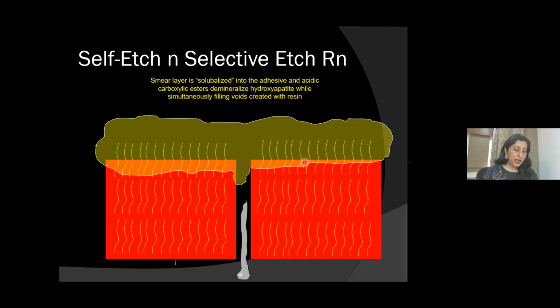And now you have to take a steady stream of air, which is applied on the surface gently until rippling motion of the bonding agent ceases. What does this mean? When you apply a gentle stream of air on the tooth, the rippling is the solvent, and it is evaporating. You have to let the solvent evaporate so that there is no white line effect in your restoration and there is no post-operative sensitivity. When you don't do this step, my dear friends, then you are bound to have post-operative sensitivity in your restorations afterwards. So this is a very important step of 5 seconds or until the rippling motion of solvent ceases.